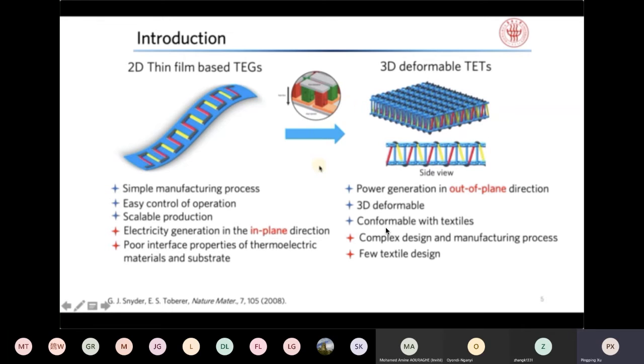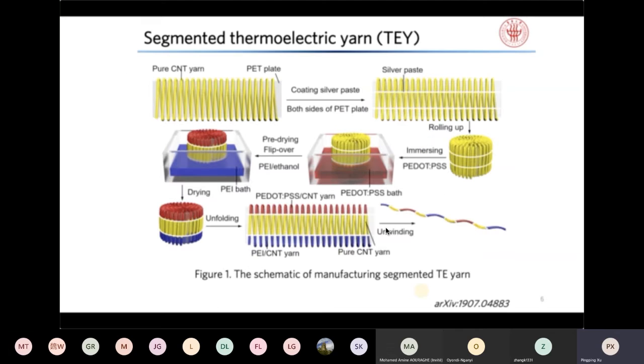And the current design of the thermoelectric textile generates power in the out-of-plane direction, or the thickness direction, and can be practical. But the current design is very complex, not a lot of people focus on the manufacturing process, and nobody understands the textile structure effect on thermoelectric power generation. So the first step, we fabricate the segmented thermoelectric yarn using highly conductive carbon nanotube yarn. We wrap it onto a PET plastic plate and then coat it with silver paste as the interface with the p-type and n-type materials, and we use the center part as the electrodes.